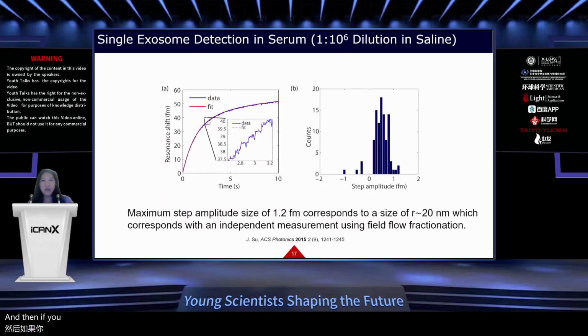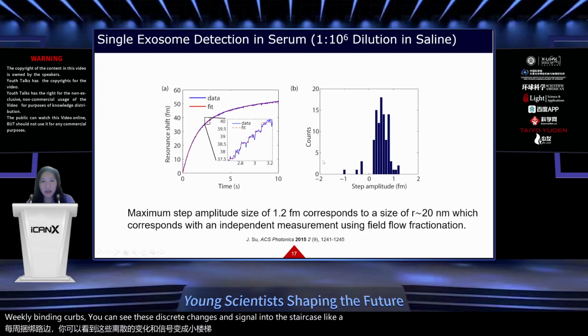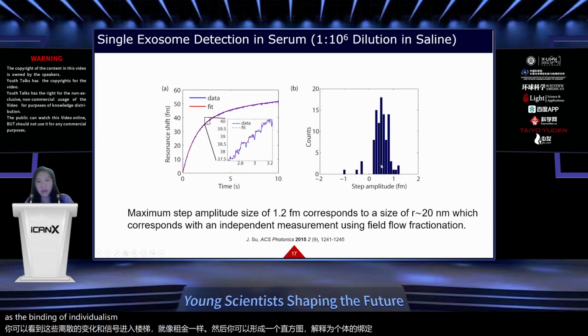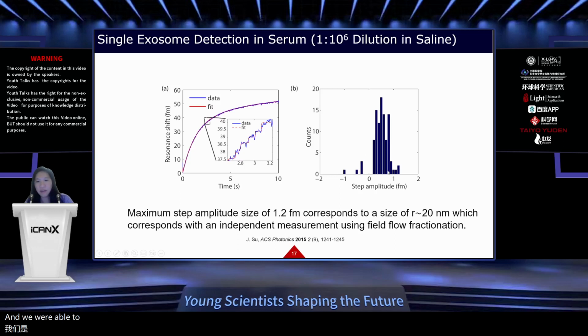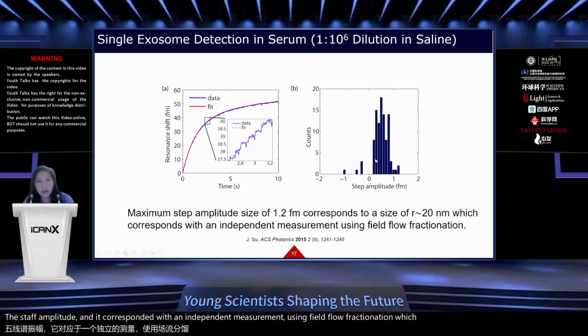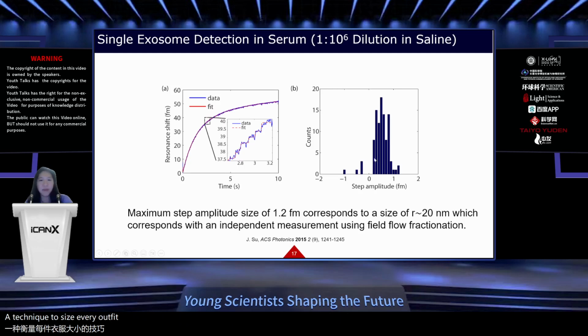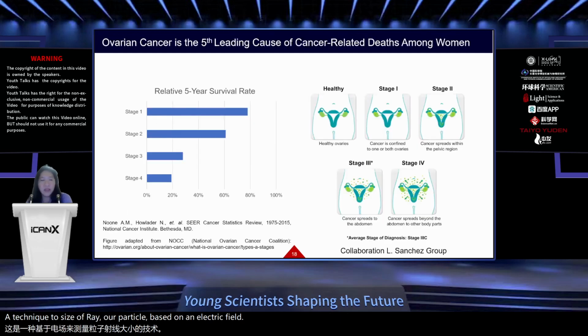And then if you individually zoom in to each of these weekly binding curves, you can see these discrete changes in signal, these little staircase-like events, and then you can form a histogram, which we interpret as the binding of individual exosomes to the surface of our sensor. And we were able to actually pull out a size from this individual height, this step amplitude, and it corresponded with an independent measurement using field flow fractionation, which is a technique to size separate particles based on an electric field. So this was our next work that we did on ovarian cancer.